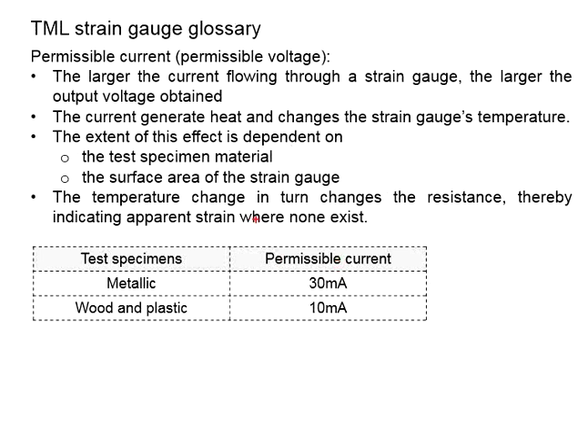Now, even though there is no actual strain here, there is a large current flowing through the strain gauge. This increases the temperature and subsequently changes the resistance. Now, as far as the measurement done by the strain gauge, there will be changes of resistance. That means the computation will give you changes of strain even though no strain exists. In order to avoid this, there is a limit in terms of the current, known as the permissible current.